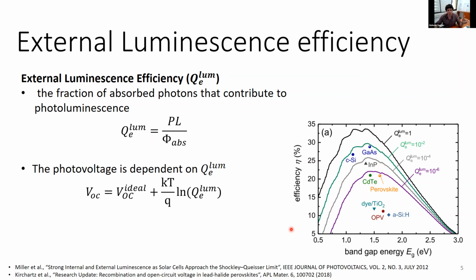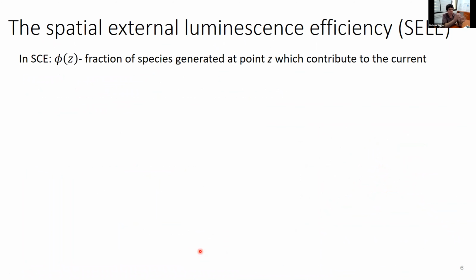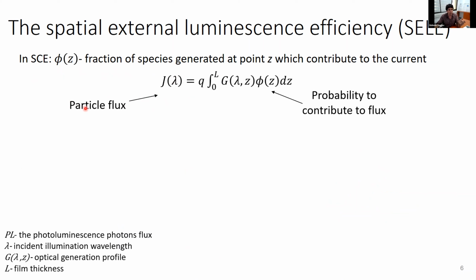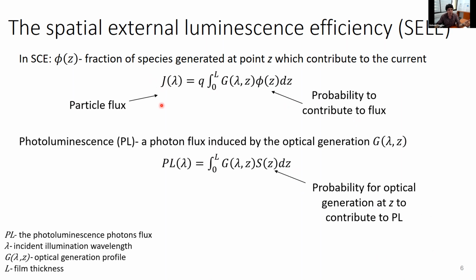So perhaps if we can map the contribution to the external luminescence efficiency, this can tell us something about the contribution to photovoltage. And maybe we can map photovoltage buildup in the device using this kind of mechanism. Taking a step back and seeing how this whole thing is put together, we talked about spatial collection efficiency. It was the fraction of carriers that are generated at some point that contribute to current. We are looking at a particle flux that is a result of the optical generation and the probability to contribute to this particle flux. So I can just perhaps replace the particle flux of electrons, and look at the photon flux out of the device and do the exact same thing. I can look at the probability for an optical generation at some point to contribute to photoluminescence.